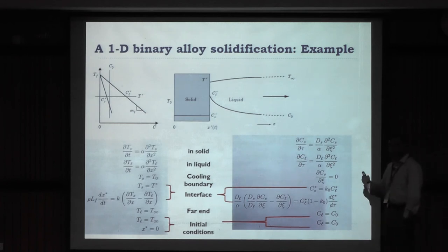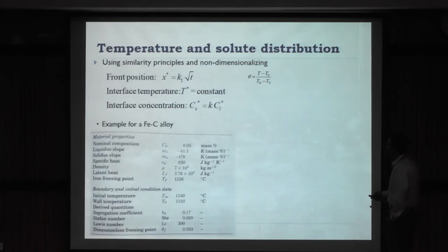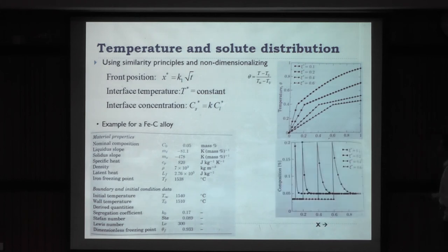Here the composition of the material is known. Sometimes it is not known, and I will describe how to model them. Initially, if the concentration is known, then through a new analytical solution you can calculate the temperature distribution as well as the concentration distribution, using suitable boundary conditions. So the temperature you will get is basically again a Stefan problem. Additionally, you are solving the composition basically.